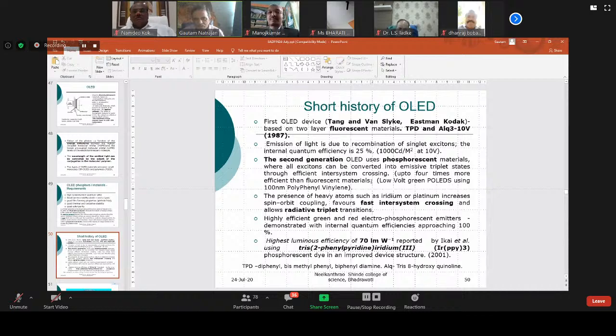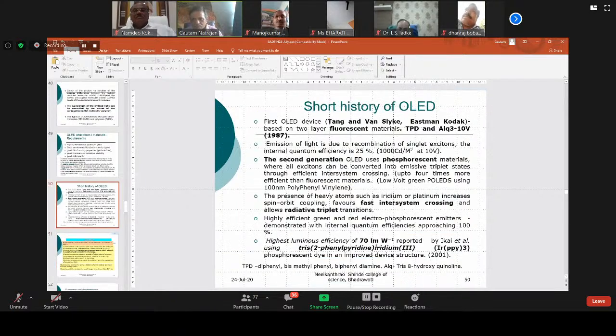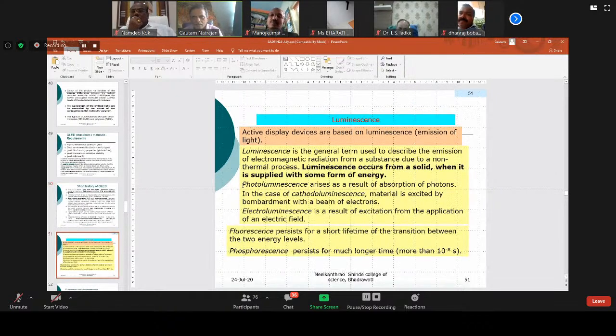The presence of heavy atoms like iridium and platinum in the complex of that OLED material will increase the spin orbit coupling, fast inter-system crossing will happen, and the triplet transition will increase. Highly efficient green and red emitters where 100% quantum efficiency can be achieved. Phosphorescent emitter. Okay. Finally, this is using iridium phenyl pyridine. They have observed 70 lumen per watt. This is a 2001 report.